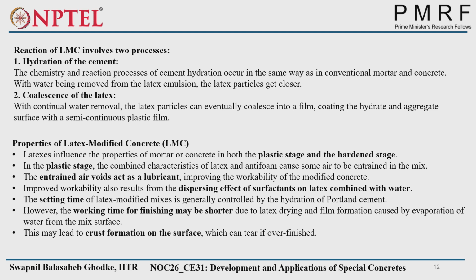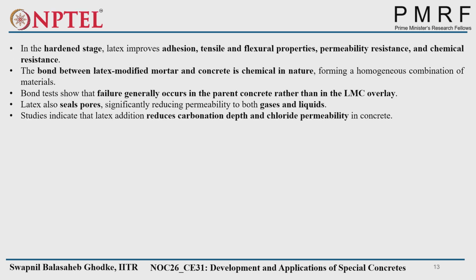However, the working time for finishing may be shorter because the latex will dry and film formation is caused by evaporation of water from the mixed surface. That will not allow more finishing time. For that purpose, the execution time will be less for this type of concrete. And once it hardens very fast, there will be crack or crust formation on the surface while finishing. But in the hardened stage, if you keep in mind all these points and complete all finishing in the plastic stage, the hardened stage will give more benefits.